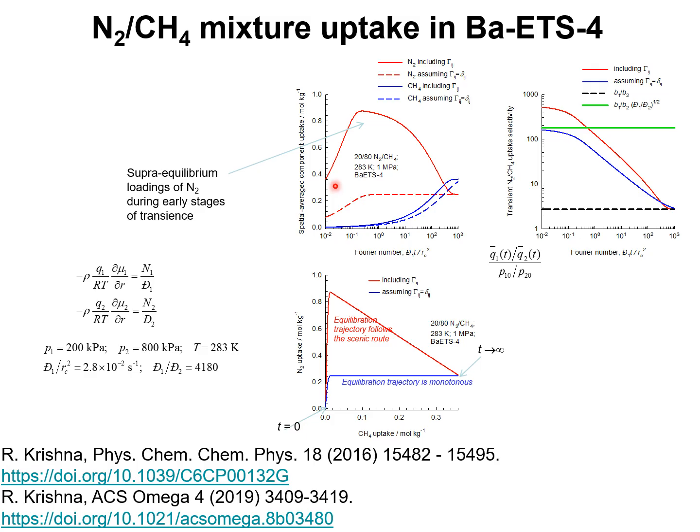When thermodynamic correction factors are duly accounted for, the nitrogen uptake shows a distinct overshoot, and that overshoot disappears if coupling effects are ignored.